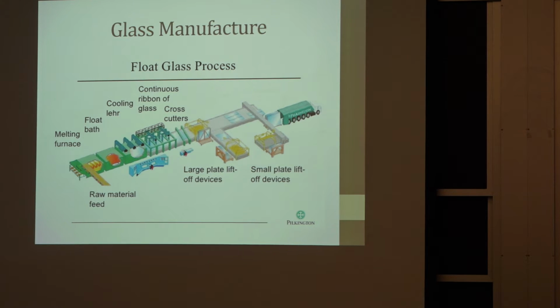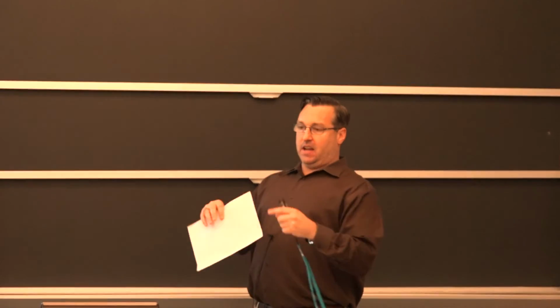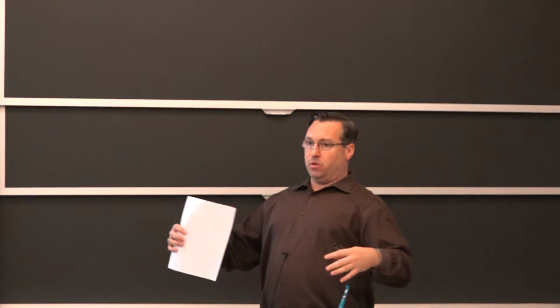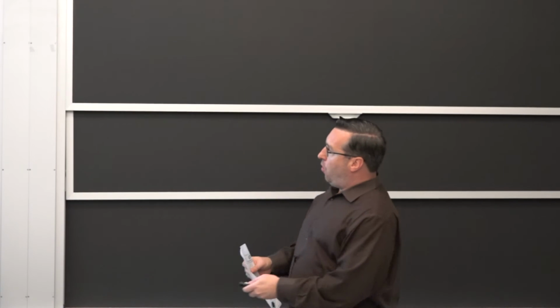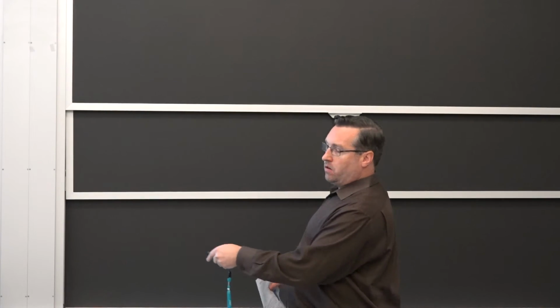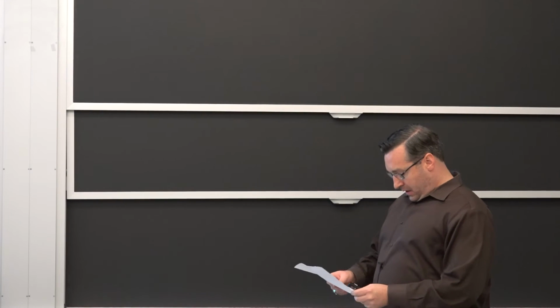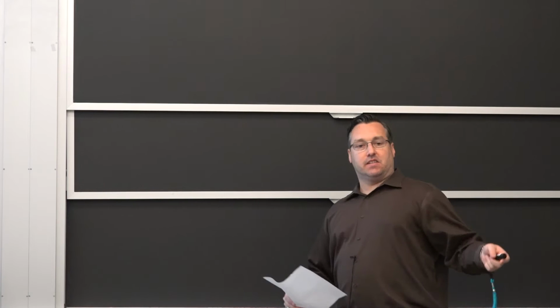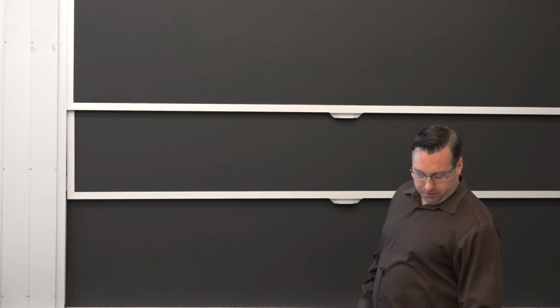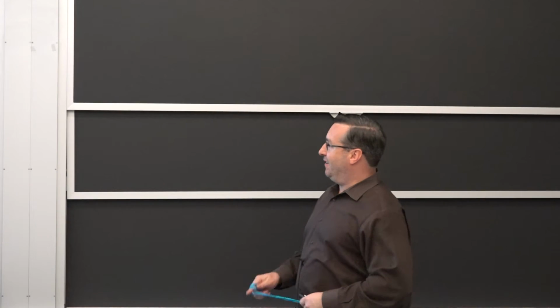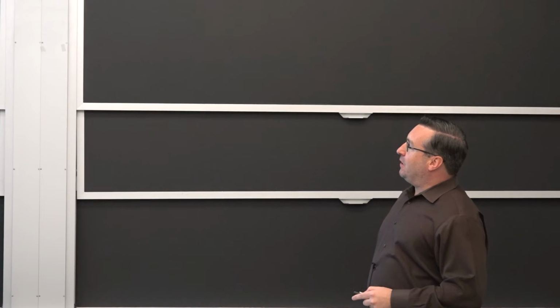What happens in the float glass process is you float the glass over a bath of molten tin. I have a video to show you in the next couple slides, but you have your molten tin, and it's almost like oil and water. You have your molten glass raw materials on top. When it gets onto the tin, because of surface area and issues like that, it will spread out and fill up this whole region of where your panels end up coming off the assembly line. Pilkington then licensed this to numerous companies and became wealthy. And I think there were some family lawsuits later on. So it really revolutionized the industry.